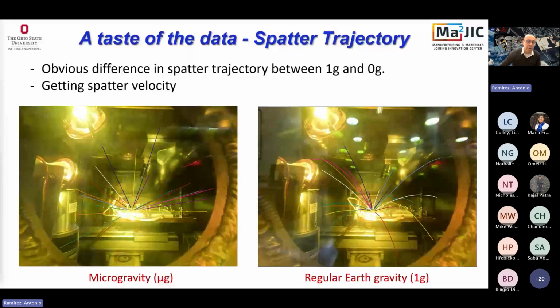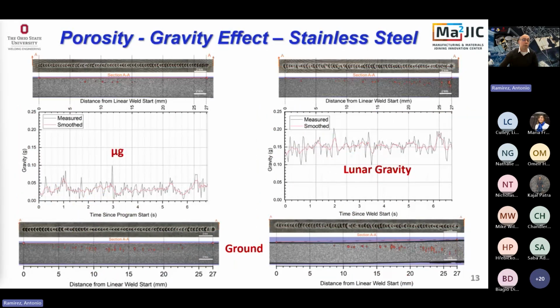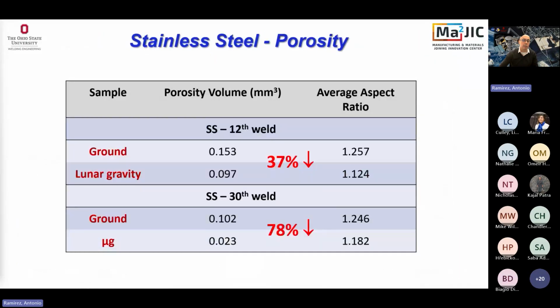Just a taste or a peek of data. You see, this is the spatter. When we're welding, sometimes metal starts flying, and the trajectory of these particles changes because of gravity. So this is nice to see happening. Other thing is, we see that the porosity, in this case on stainless steel, changes. It actually changes differently between different materials and different gravity levels. These red dots in here are the pores that we are seeing during the microgravity experiments.